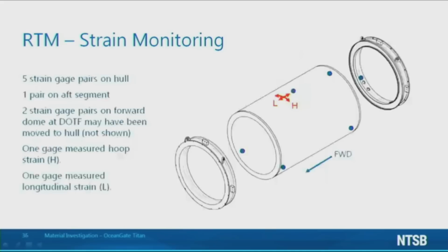There were 8 strain gauge pairs on Titan. 5 gauge pairs were located on the hull, and 1 pair was located on the aft segment. 2 gauge pairs were originally located on the forward dome during testing at the Deep Ocean Test Facility and may have been moved to other locations on the hull. As illustrated by the red arrows on the image, 1 gauge in the pair was aligned in the circumferential direction and measured hoop strain. The other gauge was aligned along the axis of the cylinder and measured longitudinal strain.